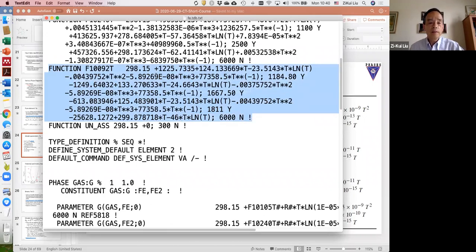So you see, from the low temperature stable one, from room temperature to 1184, that transforms to FCC. You have one function. Above the transition temperature, it becomes metastable, you have another function. Then above melting, you have another function. So you get different ranges because it behaves differently at different ranges. Some places you have no data, so you have to do the estimation.